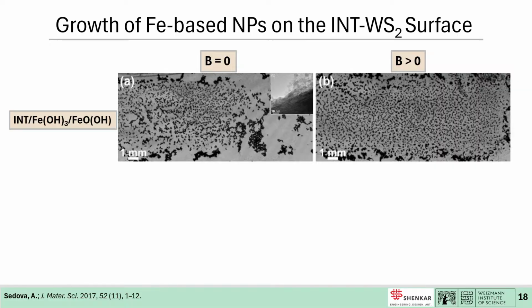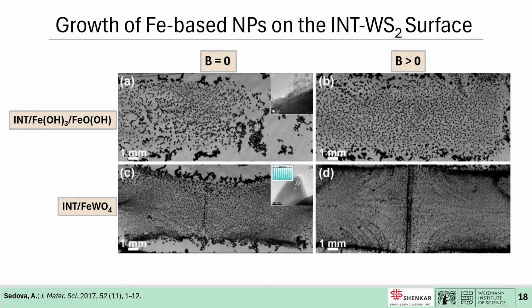So the idea for me to start depositing magnetic nanoparticles on the surface of the nanotubes was that I was trying to align those nanotubes inside of the polymer and try to achieve percolation that way, or by alignment you can achieve different mechanical properties. But we didn't succeed to do it with polymer as it was too viscous, so we made a solution, basically drop casting it onto a glass substrate and applying a magnetic field. With iron hydroxide nanoparticles, we just saw that there is better dispersion, but there is no specific orientation. So we did it with nanoparticles that we annealed, the iron tungstate, and we could see something reminiscent of the magnetic field.